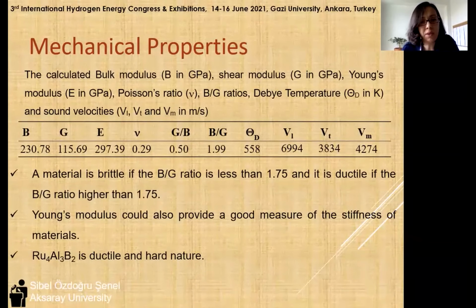A material is brittle if the bulk modulus to shear modulus ratio is less than 1.75 and is ductile if the ratio is higher than 1.75. For the ruthenium-4 aluminum boride compound, the ratio is 1.99, so it can be said that the compound is ductile. Young's modulus could also provide a good measure of the stiffness of materials. Ruthenium-4 aluminum boride is hard in nature.